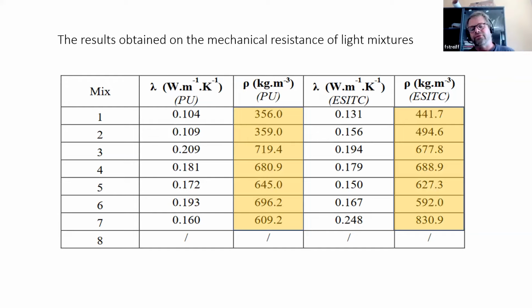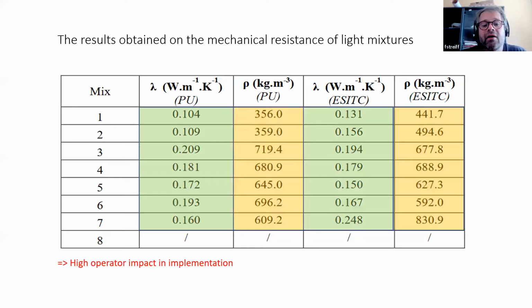Here you can see that even if the soil was exactly the same, even if the clay content was exactly the same, the water content was exactly the same, we managed to produce samples with very various density, meaning that for light earth, the implementation process has a very huge impact on the density and, of course, on the lambda value results. So it means that for the light earth, more than the proportion of the materials, it's really the way that builders will implement the material, which will produce the good properties of the wall, the good thermal properties of the wall.